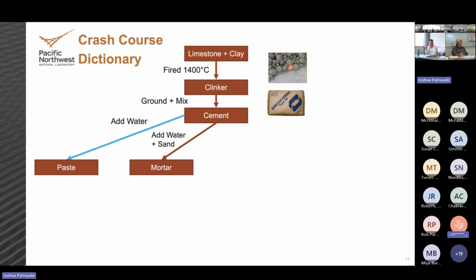You get a relatively thick mixture, and this is what you use to hold bricks together. The reason for it is you're not having large aggregate in there to push your bricks apart. You can get anything nice and level. It's got good binding properties, but that sand is filling up space. So about 50% of the mix is sand. Therefore, using 50% less cement, your costs are going farther. That's why you use mortar to hold bricks together.